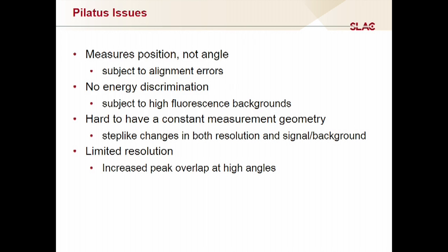And you do end up with somewhat limited resolution, and so you might end up with more peak overlap at the high angles. In powder diffraction, the density of peaks grows as you move to higher and higher angle, and you start to get peaks that overlap quite significantly. And so if you have poor resolution, that problem gets exacerbated.